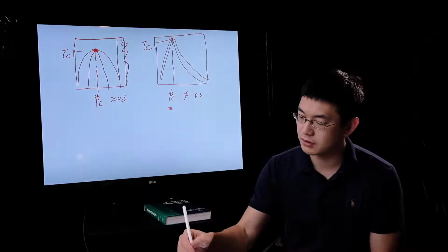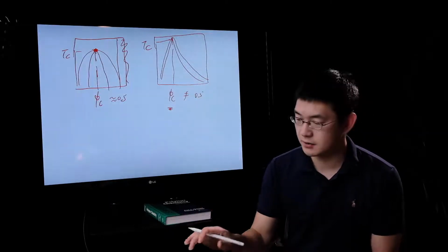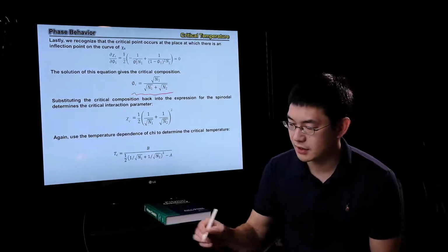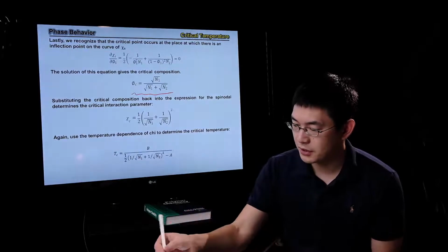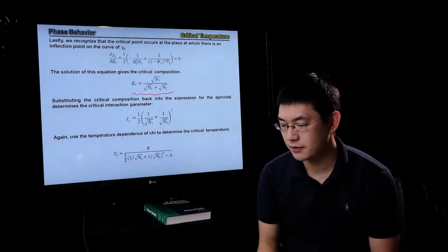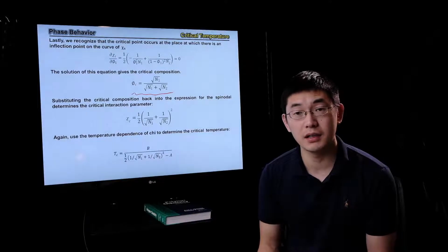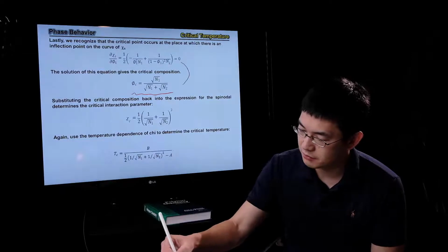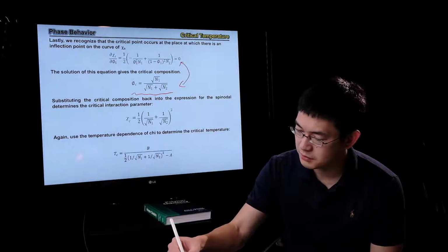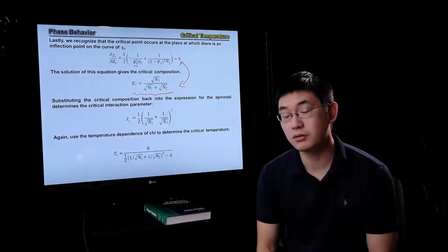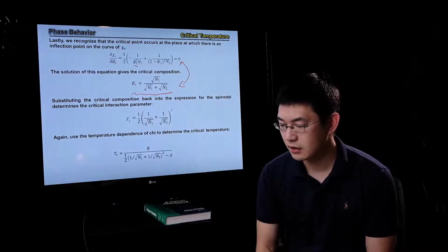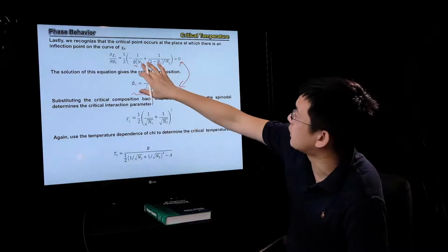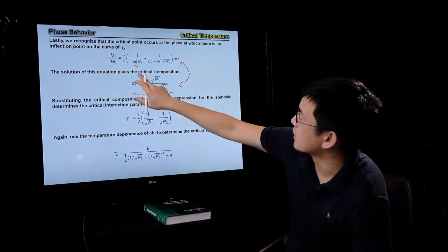And this is where we're going to also talk briefly about what the phi c value is. So let's go back. The phi c value can be defined using the equation above, where the first derivative of the Flory-Huggins parameter is equal to 0. Using that relationship, we can back-calculate what the phi c would be at these critical data points. The equation is quite simple. What you need to do is rearrange it and apply n1, n2.